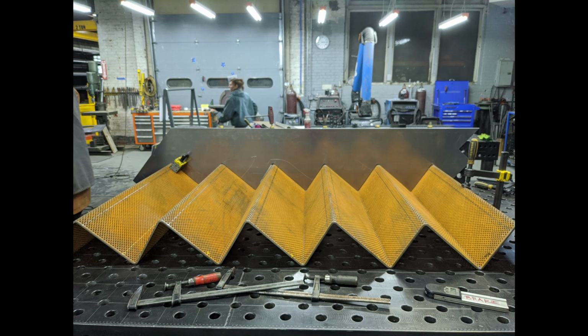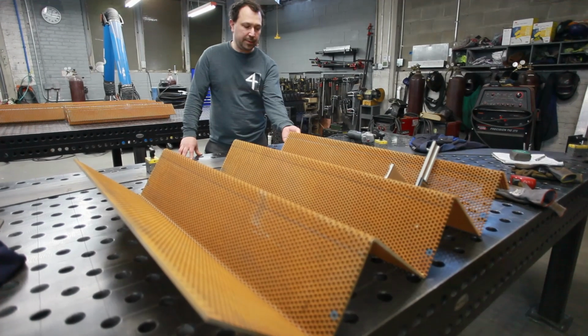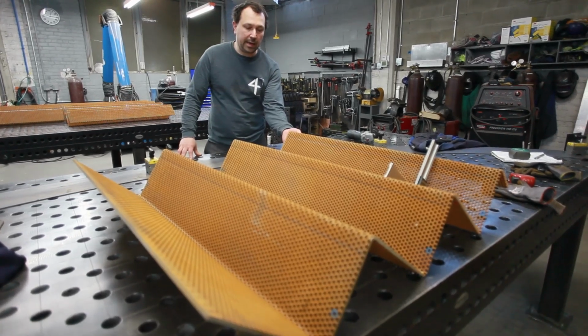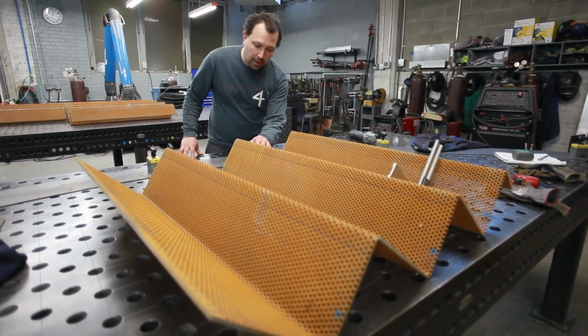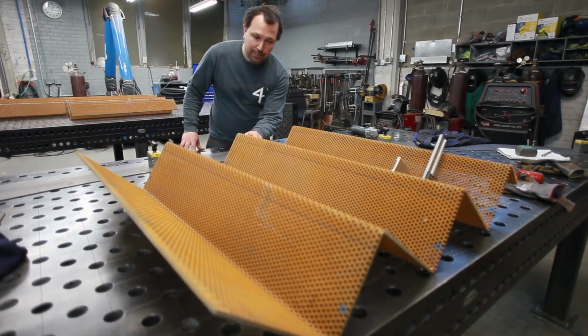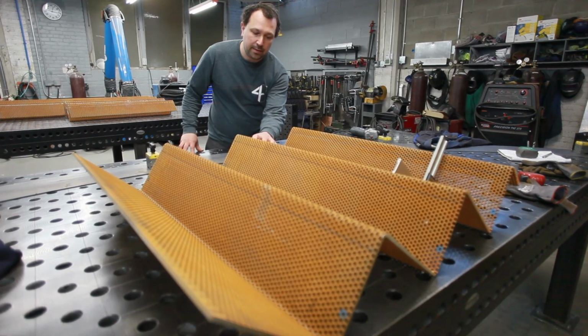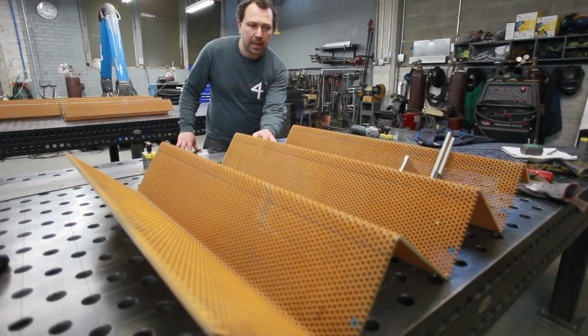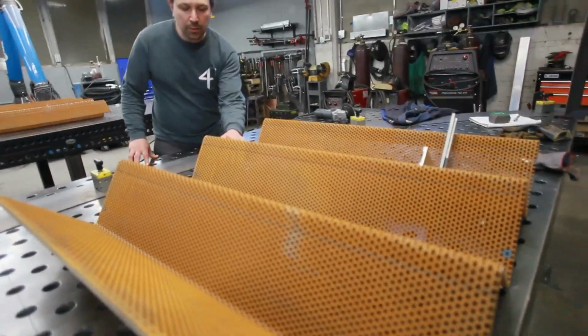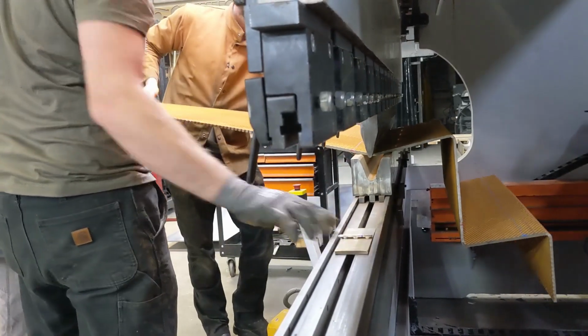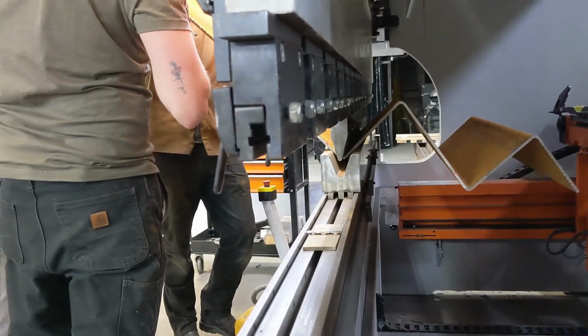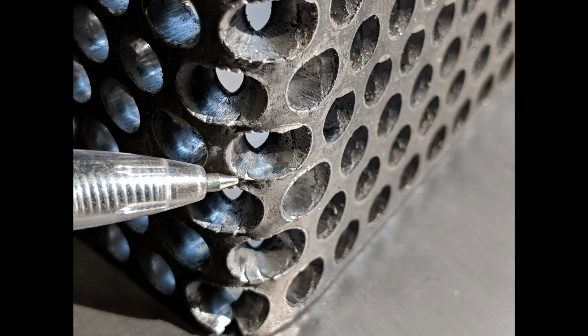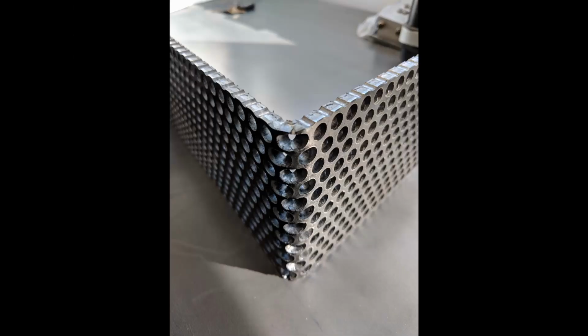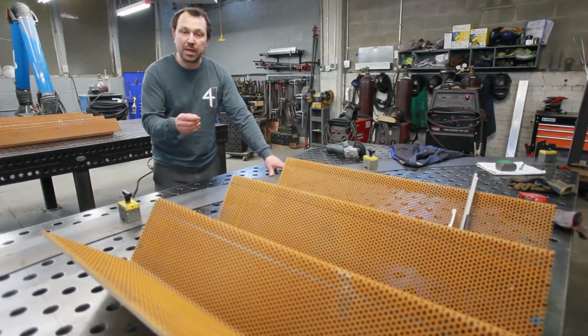One thing about the material itself is that the perforations, because they're punched and not, let's say, water jet cut or laser cut, are larger on the bottom than they are on the top. Also, during the perforation, the material seems to get work hardened. When we got the material to do some sample bends, even though we're using a very large radius punch and die on our set, we were getting cracking almost exclusively on the back side of the material, where there is less material because of the punch hole being bigger on that side.